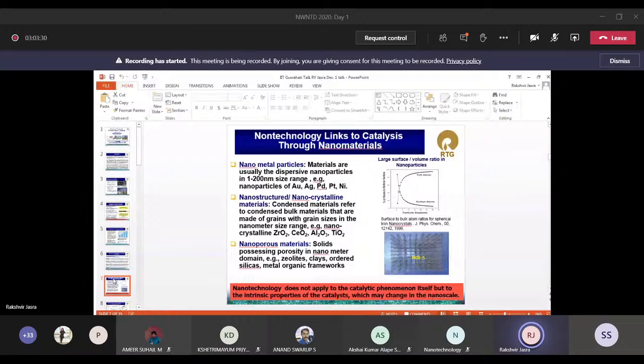Earlier also people were making these catalysts in nano size, but the control on the size and shape of the nanoparticle used as a catalyst was not there. But today we have arrived at a position where we can control the size of these particles, the shape of these particles, and also the facet of these particles. So this is one area in which nanotechnology has made a huge impact on nanometal particle based catalysis.